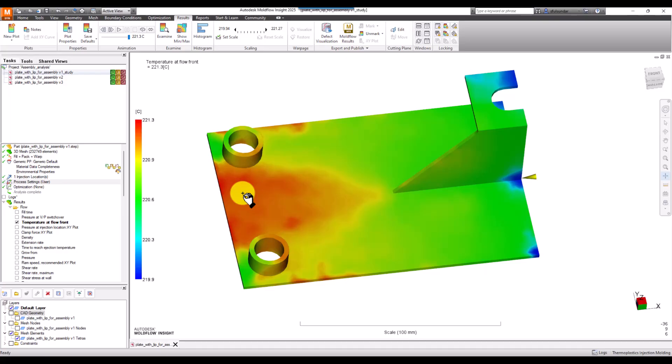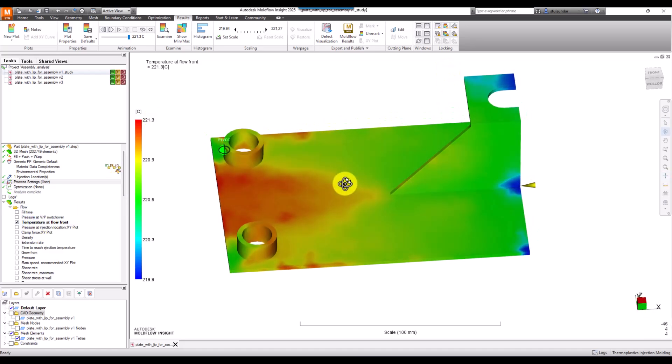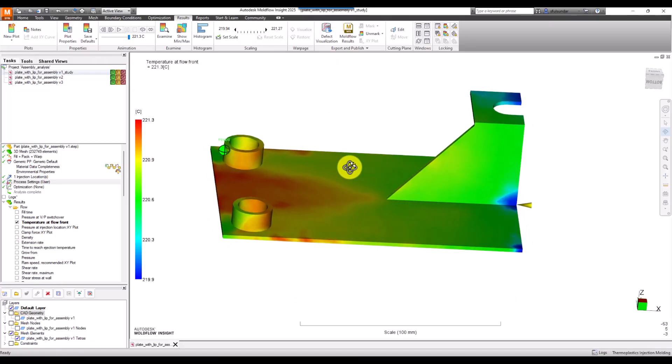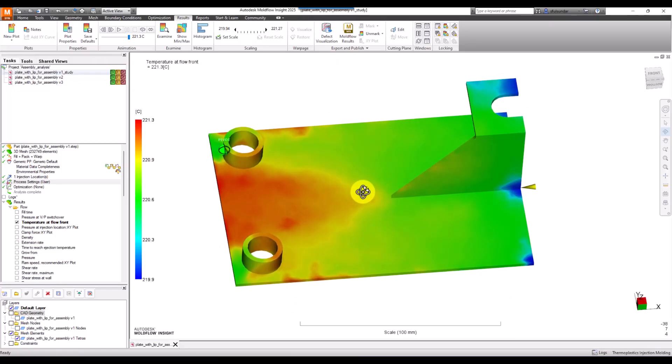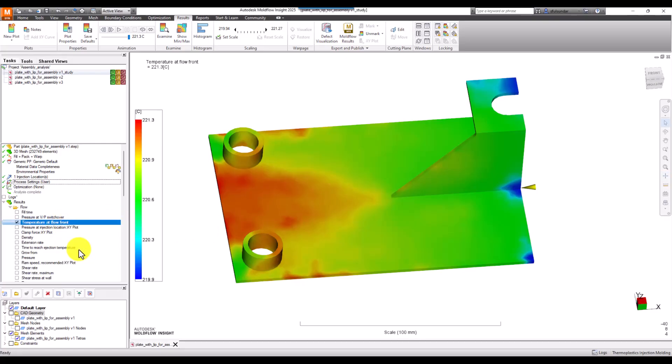There's blue, green, and red patches it's showing, and I can see patchiness over here. I can see the patchiness because my legend scale is small. But if this were bigger, I wouldn't be able to see the patchiness. So always try to fit the scale in an appropriate way if you really want to see surface defects caused by temperature variation in the part. This variation would be caused by shearing at narrow sections or fast movement of polymer as it rushes into the cavity. For now, let's understand this is a rise in temperature because of shearing.